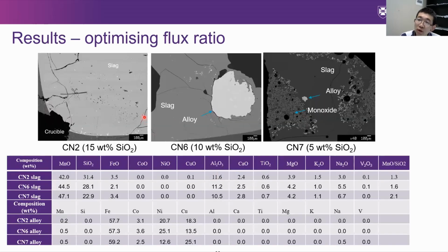So this is the result where we optimize the flux. By increasing the flux, we still have solid in the slag. This is not favorable because it will give a very high viscosity of slag, and it will be very difficult to tap the slag and separate it from the alloy. By increasing the silica, we can get a full molten state slag, and also the alloys are produced, with copper oxide, nickel oxide, and cobalt oxide fully reduced from the slag.